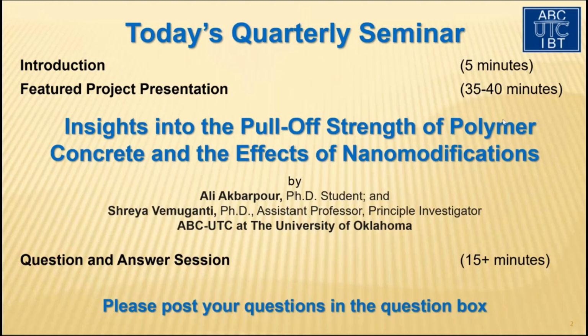Did you investigate the effect of temperature on the bonding of the polymer to the concrete? So that is a great question. In the entirety of the project, we've had several seasons that went in and out, right? We had cold temperatures and heated temperatures. So we want to say that this particular polymer concrete does not work well beyond a temperature of 90 F. So the storage and application is not recommended beyond 90 F. So that is my conclusion. Okay.